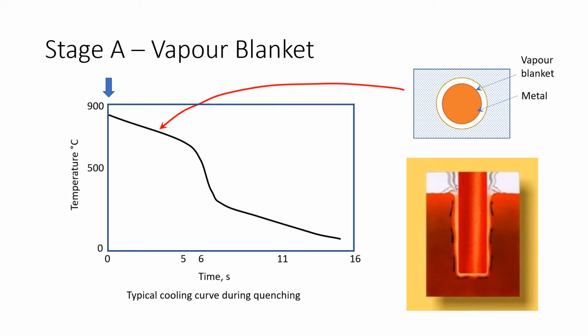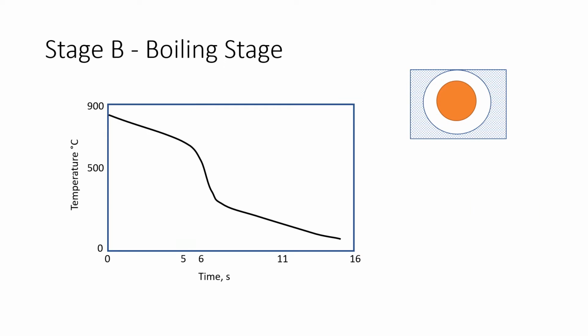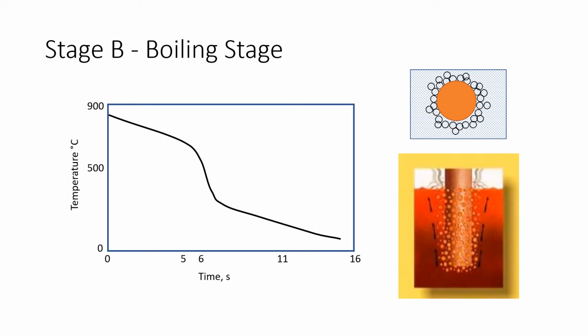Since vapor films are poor heat conductors, the cooling rate is relatively slow at this stage. Ideally, the vapor phase will be as short as possible to come up with steel with high hardenability. During the boiling stage, the vapor blanket is broken intermittently, allowing the coolant to come in contact with the hot surface at one instant, but soon being pushed away by the violent boiling action of the vapor bubbles. The bubbles are carried away by convection current and the liquid touches the metal again.